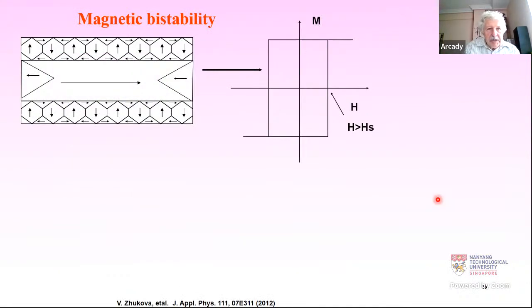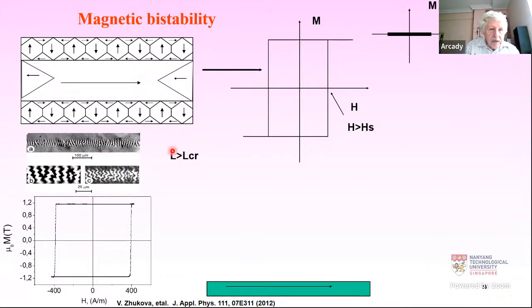So first I will focus on magnetic bistability. I already explained a little bit. In fact, this effect is related closely to the domain structure of our material. This is the schematic picture of the domain structure of iron-rich microwires with positive magnetostriction. And this squared hysteresis loop is attributed to a single axial domain, whose origin is exchange energy, because in long and thin samples the magnetization tends to lie in the axial direction. And therefore, the length of the sample is important because of the demagnetizing field and these closure domains. And if the ratio between length and diameter is high enough, we can get this squared hysteresis loop, the real hysteresis loop.